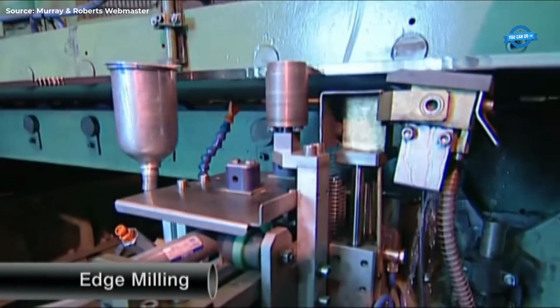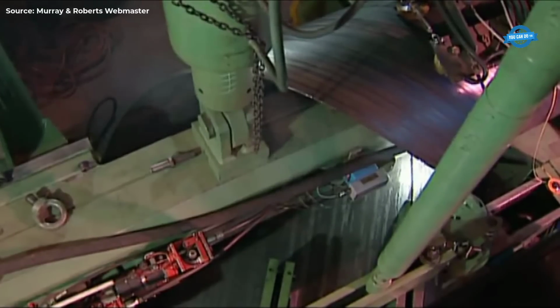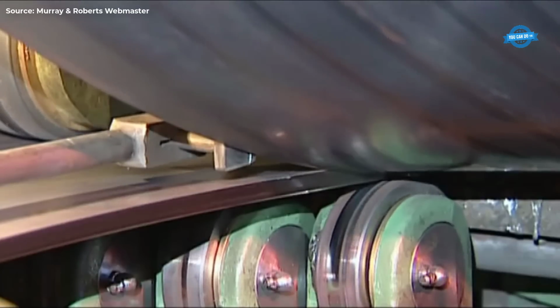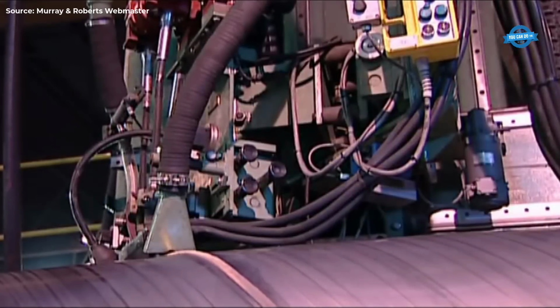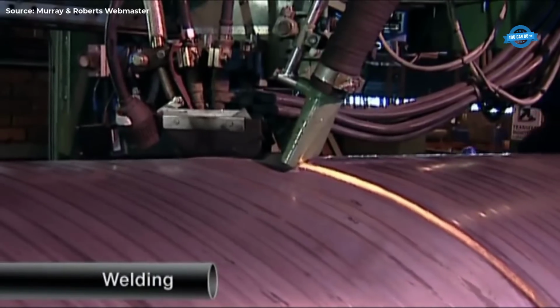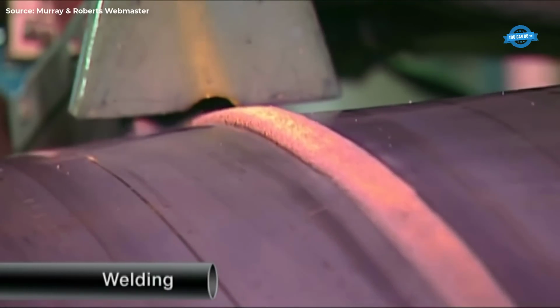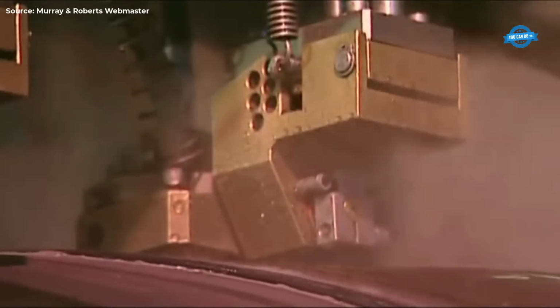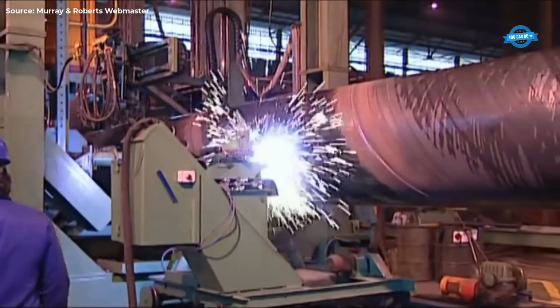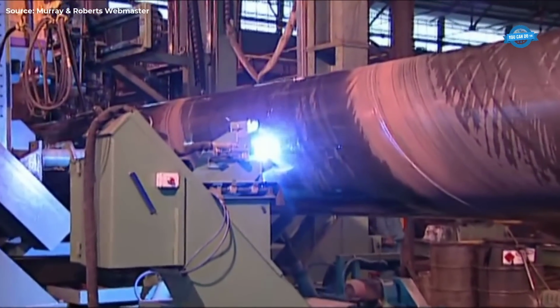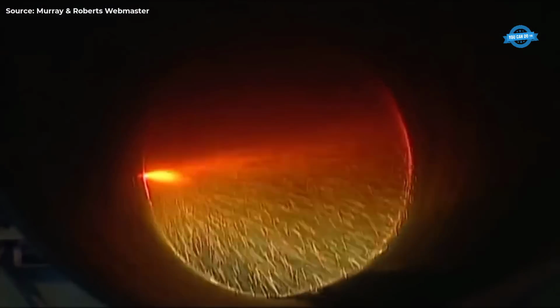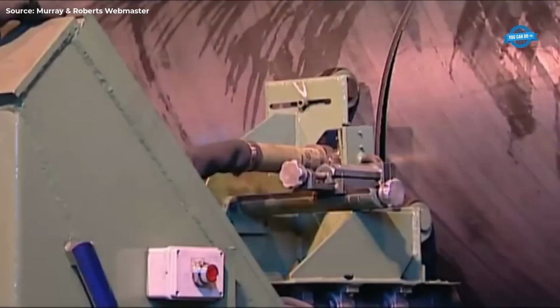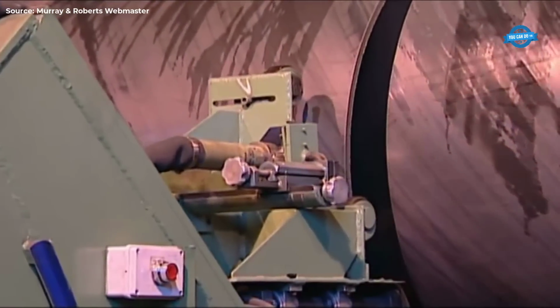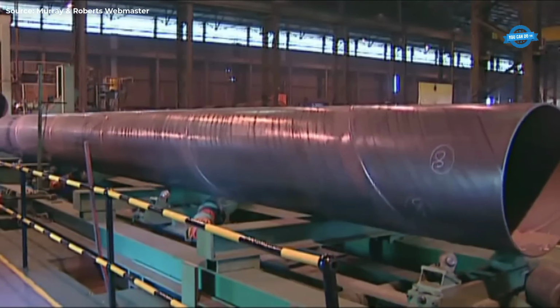Steel pipe, using the Submerged Arc Welding process, SAW, is manufactured by Hall Longmore to a diameter ranging from 660 mm to 2,540 mm. Steel pipes are fabricated from steel plate bent to a circular form, or they may be continuously produced from a coil of steel strip bent to a spiral and butt welded along the spiral seam. Joints between coil ends of spiral welded pipes are known as skelp end welds. Butt welded pipes are made from rolled strip with a longitudinal seam furnace butt welded by a continuous process.